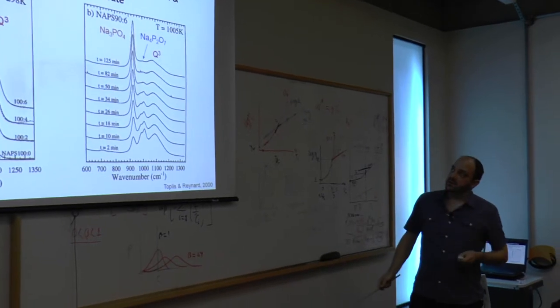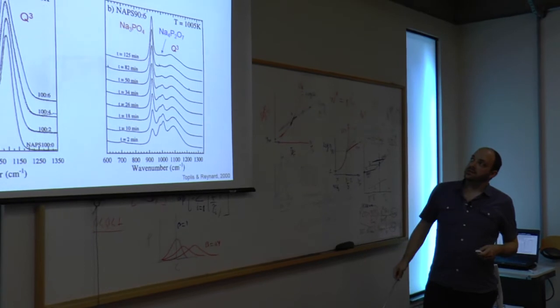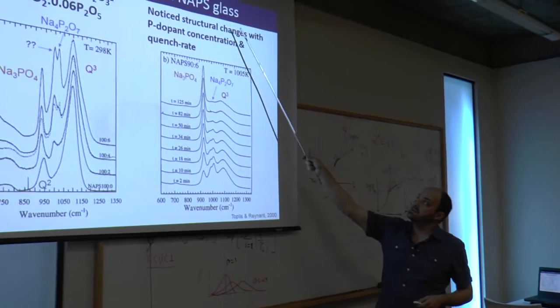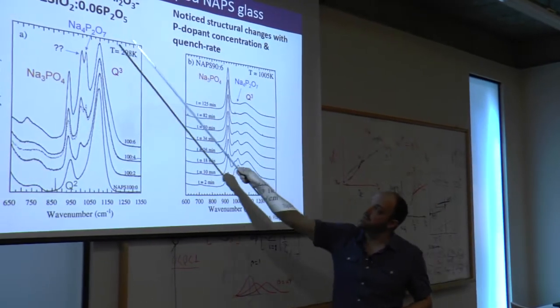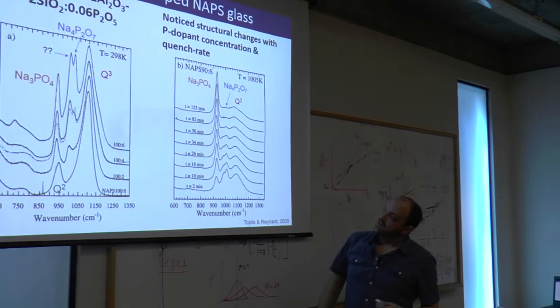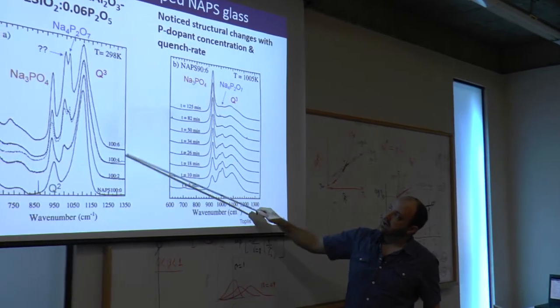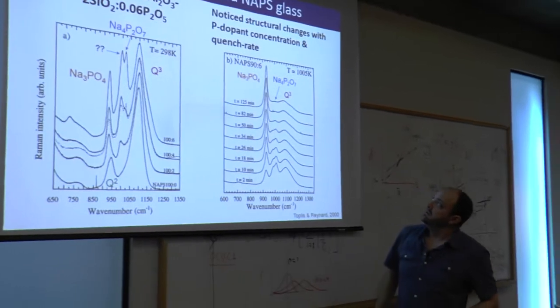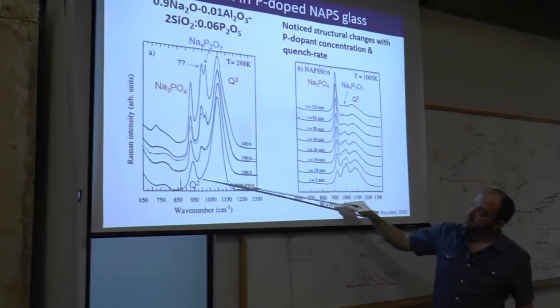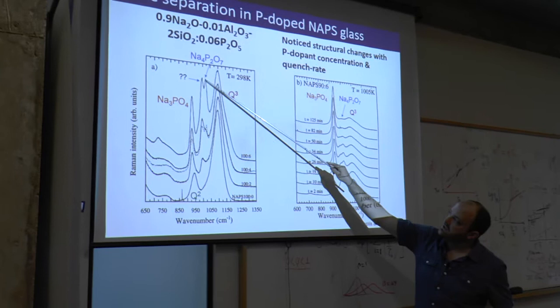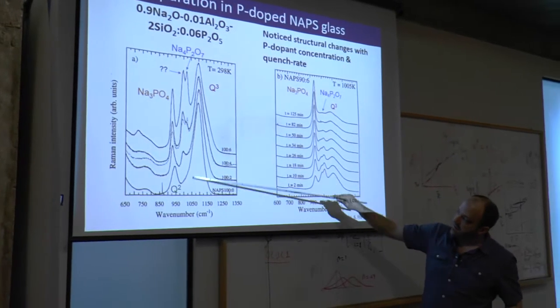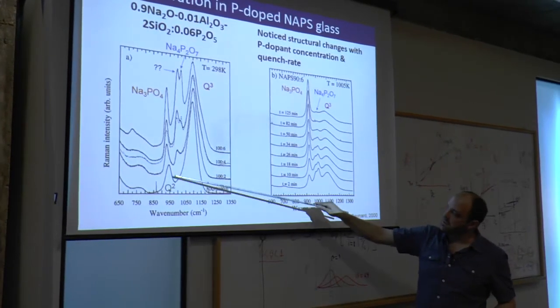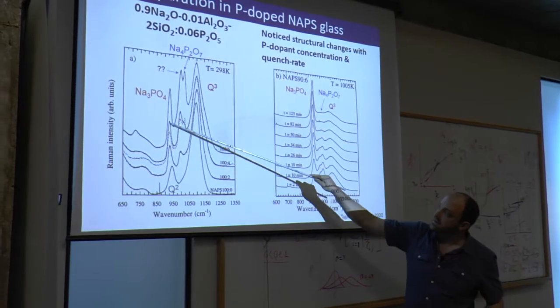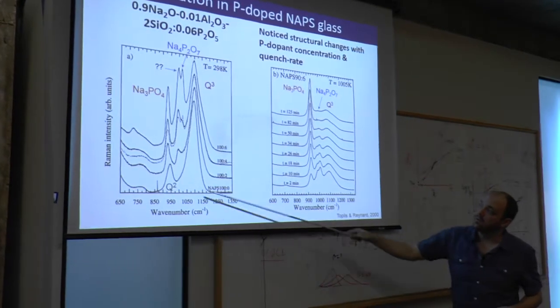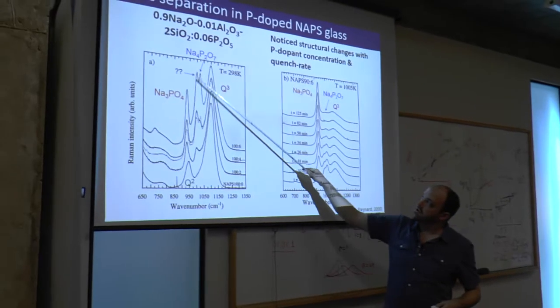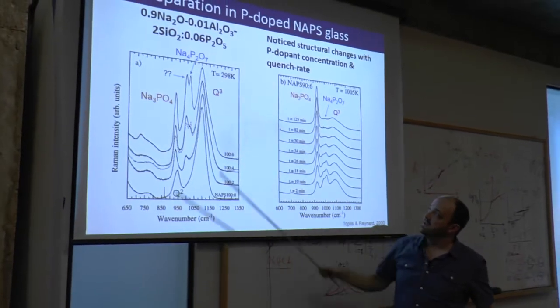Here's another example. This is of sodium aluminum phosphate glasses, phosphosilicate. Here's the composition here. And they noticed that as you added small amounts of phosphate, you had quite strong changes in the high frequency zone. You have the addition of these peaks. And instead of just having the Q3 and Q2 bands here, you also saw a shift of this to lower frequencies. And they identified these additional peaks as these phases here.